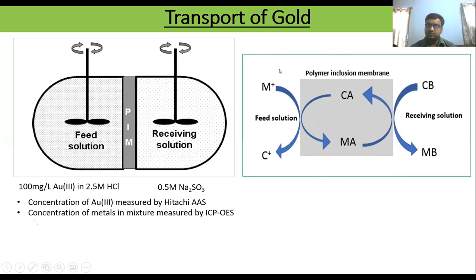I mentioned before, if you have some metal and you have some carrier agent over here, this metal will bind with this carrier agent and release a counter ion. And this metal-extractant complex will diffuse through this membrane and go to the receiving side, where it reacts with the chemical present in the receiving side and releases the target ion, the metal, and again regenerates the extracting agent. So this agent again moves through this membrane and collects another metal and comes back to the feed side.